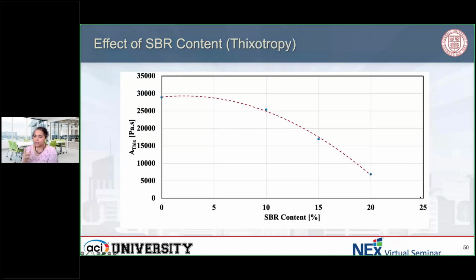So because the large scale printing system that I've been showing you with X3, we usually, when we print, we are mixing batches of about 50 to 75 liters, and we print about 200, 300 liters. But then when you're just doing material development, in this case, we're trying to see, can we print with SBR, and to what extent can our material properties improve? This is more like experimental studies, so we don't want to be experimenting with 200 liters of material system.